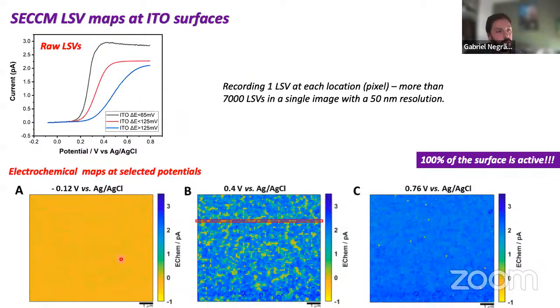On one of those scans of this area, which is almost 10 by 10 micron, we have more than 7,000 voltammograms, so more than 7,000 pixels in this image. Every pixel, we're assuming, is 50 nanometers, so assume that the pipette meniscus wets a little bit. I think there were only 4 pixels that didn't give an electrochemical result. So for every single one of those pixels, we could record a CV. Because this is a CV, I can actually map each potential; those are just snapshots from a movie, where I can map each potential to the surface area.